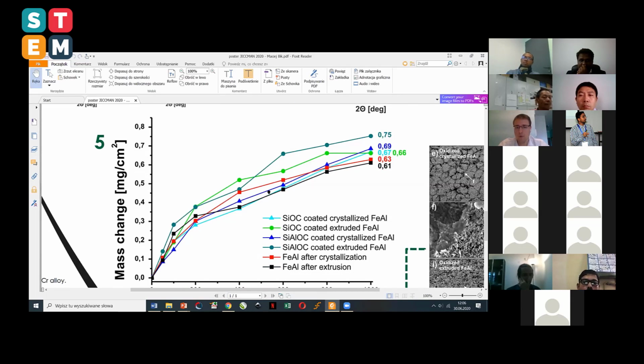And also, the second interesting feature is really beautifully shown: the theta to alpha alumina phase transition, because of decreasing intensity of a reflection coming from the theta phase and simultaneous increasing intensity of a peak coming from the alpha alumina phase. So right now I would like to move on to the second part of the study, which is the